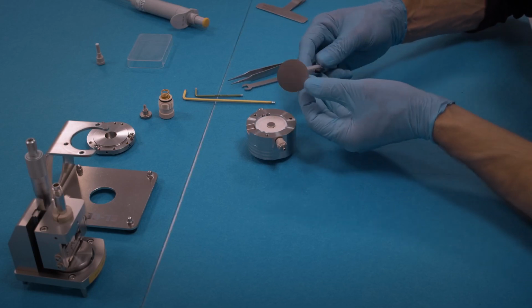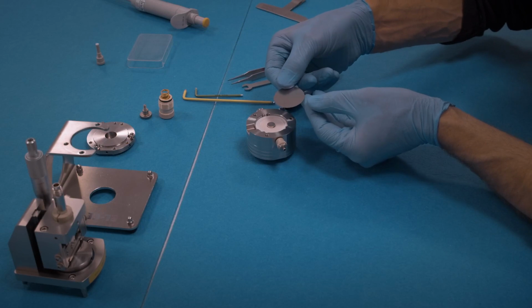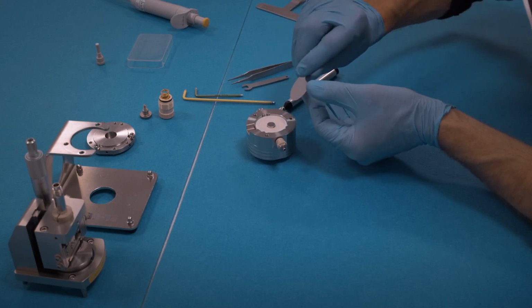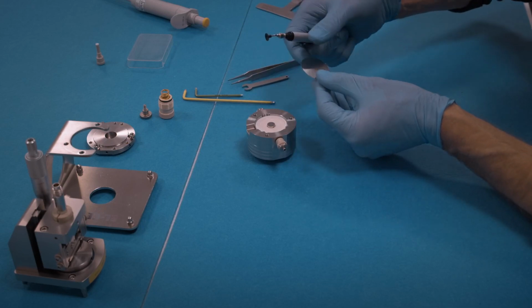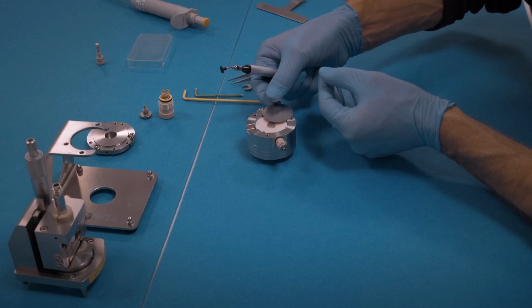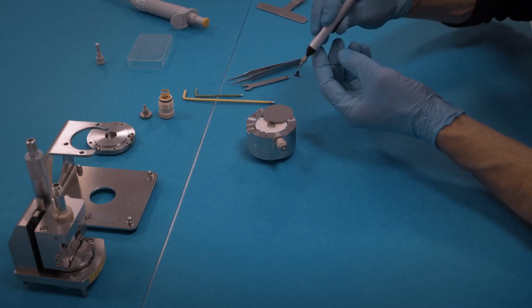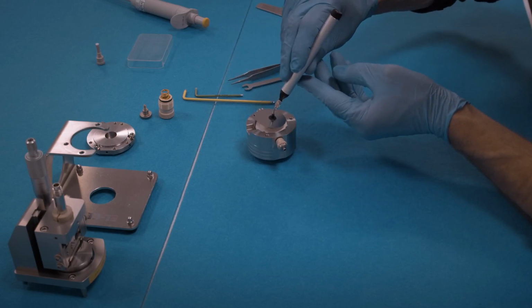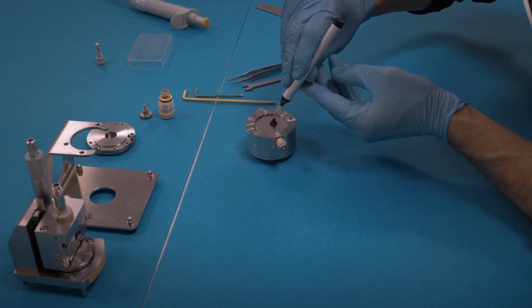Now we place the metal foil on top. Always use a fresh one. Dispose after use. Make sure that it is perfectly flat, not bent, and that there's no indent from a previous experiment.